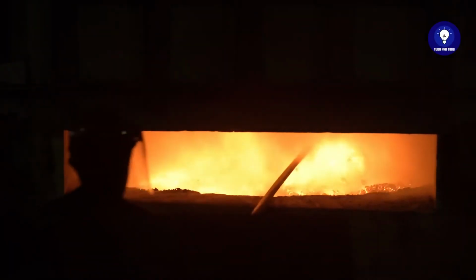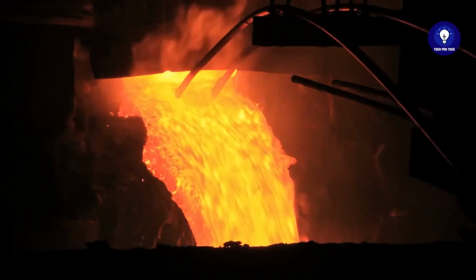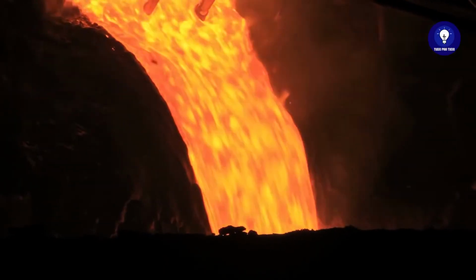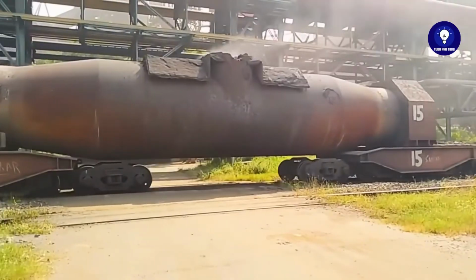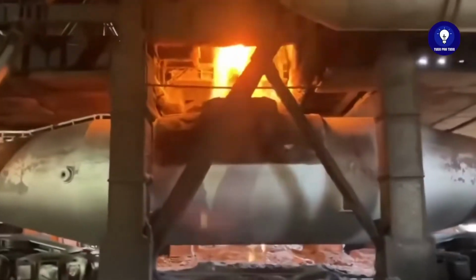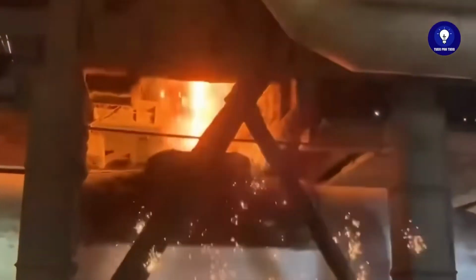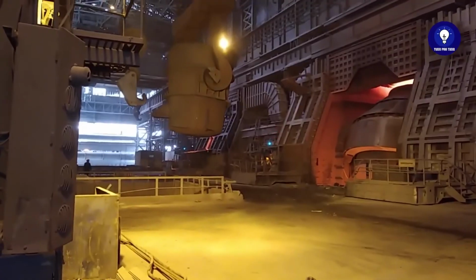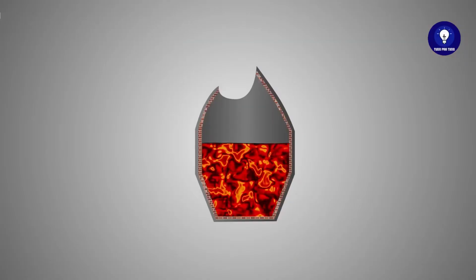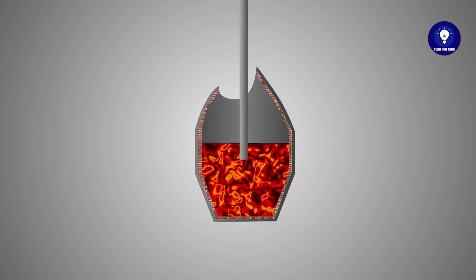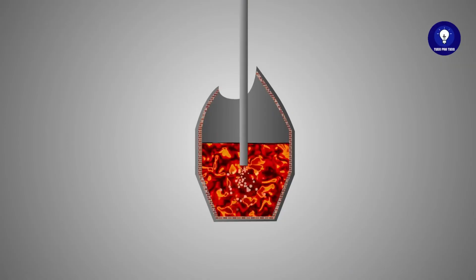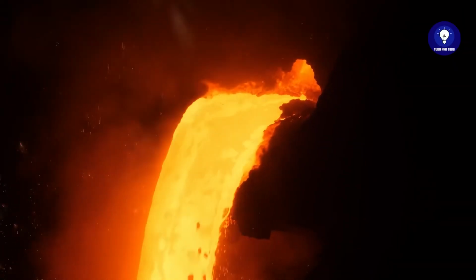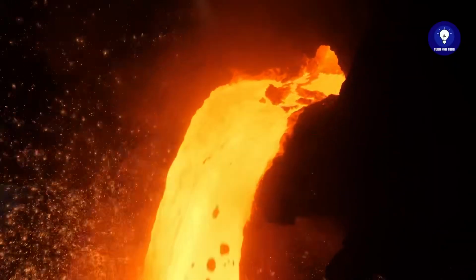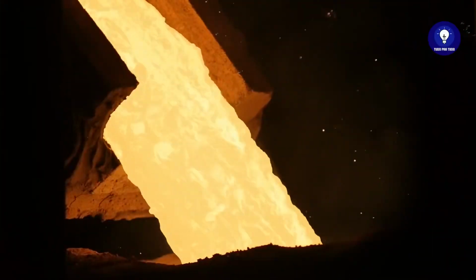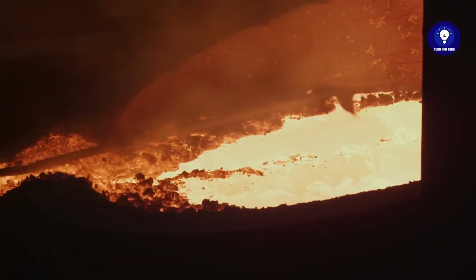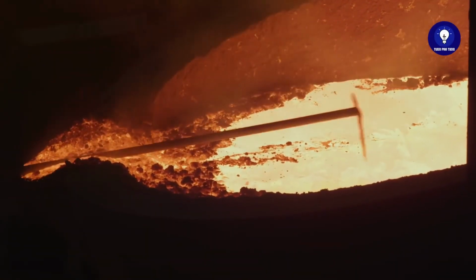Periodically, technicians open a hole in the refractory wall and watch a luminous river flow into channels and then into torpedo cars. These wagons are real thermal flasks on rails, insulated with special bricks, capable of keeping the metal in a liquid state during the journey to the second key equipment, the basic oxygen converter, known by the acronym LD. Inside an external steel shell and lined with bricks on the inside, the pig iron receives a jet of pure oxygen blown through a tube called a lance. In less than 20 minutes, the reaction reduces the carbon in the metal from about 4% to values close to 0%, turning the pig iron into steel. At the same time, new slags are formed that absorb sulfur, phosphorus, and other undesirables.